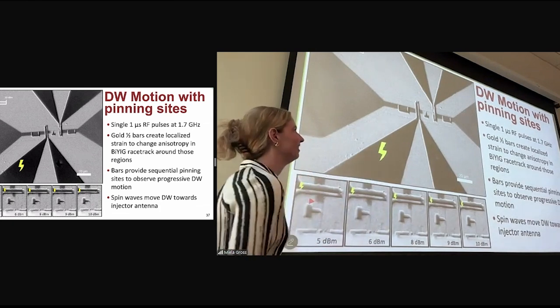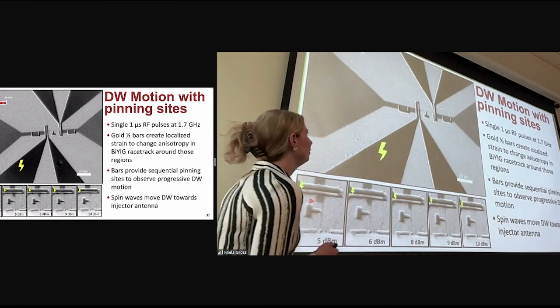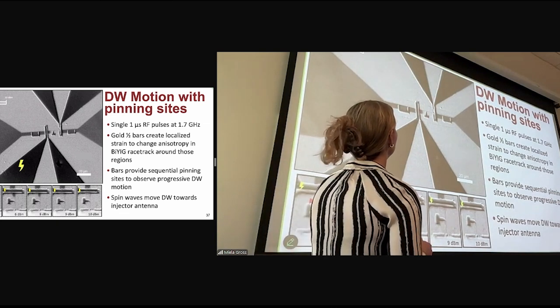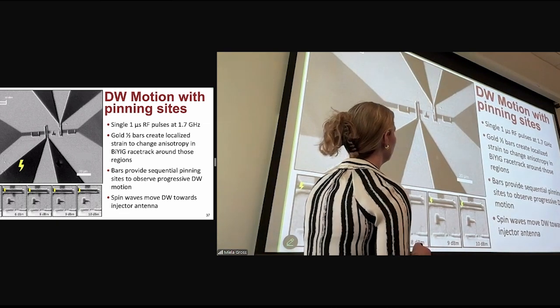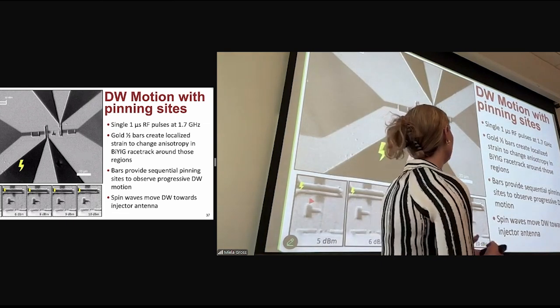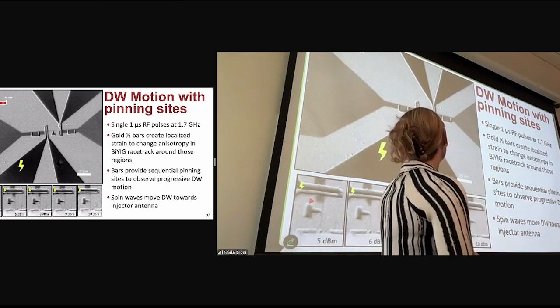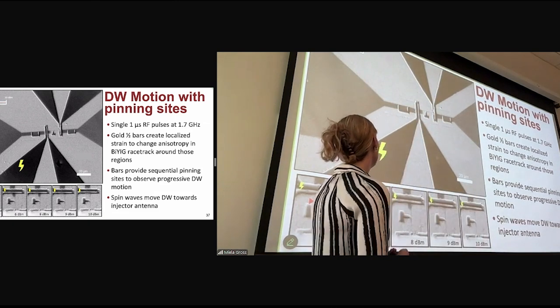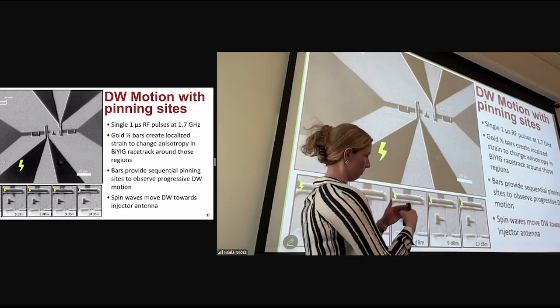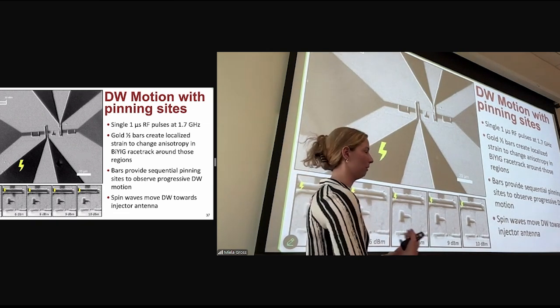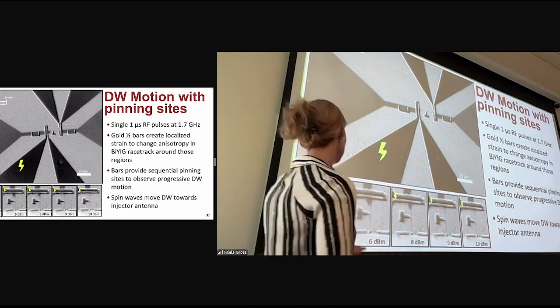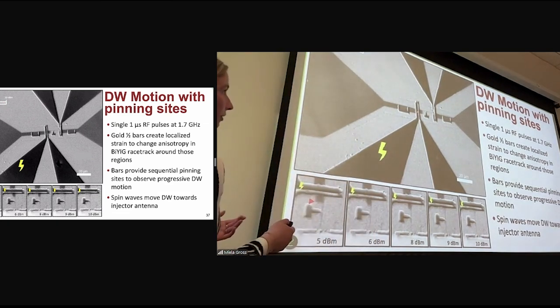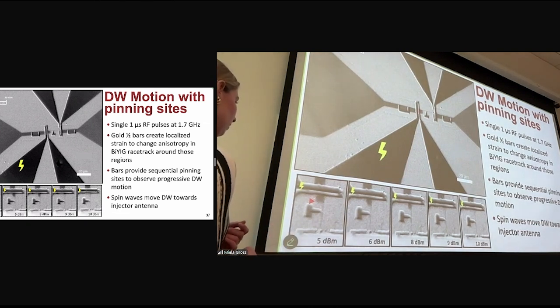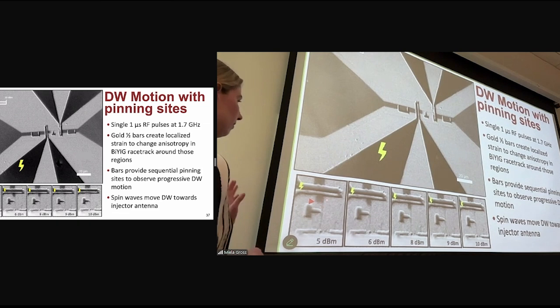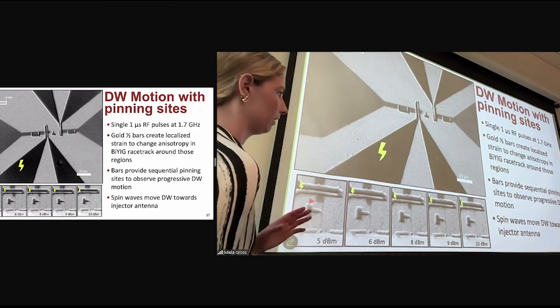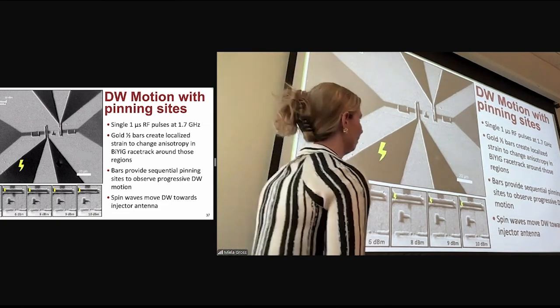So now I'd like to show you all some more motion pictures of the domain wall motion in these new devices. And you'll notice we have these little half bars patterned here. And these half bars are used, again, to create that little localized strain, to change the anisotropy locally in those regions and provide pinning sites. And basically, what that allows us to see is the sequential pinning sites of the domain wall to observe progressive domain wall motion. And that's exactly what this movie shows here, the domain wall slowly inching towards the injector antenna. So we see it'll just be pinned about 4 microns away from the antenna initially, and slowly start to move all the way under that injector antenna.